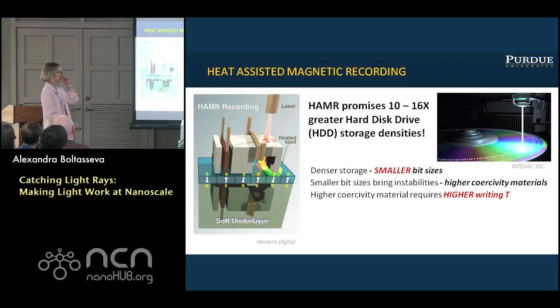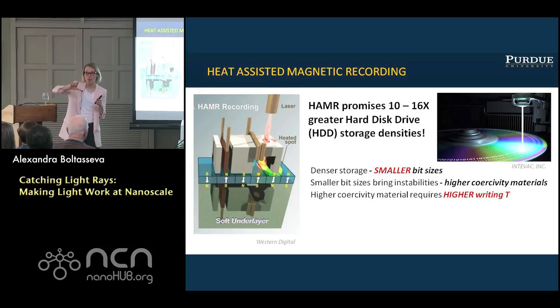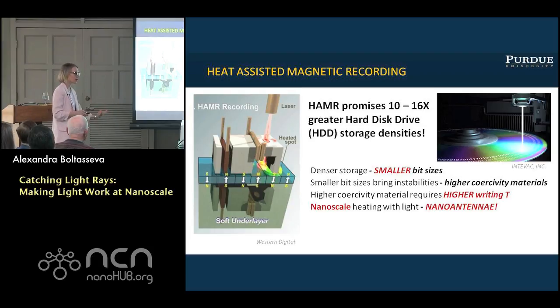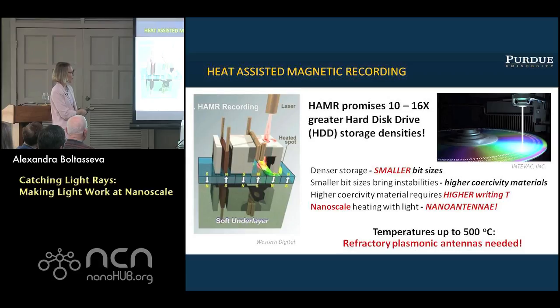In order to enable this technology, if you want to reduce the size of your bit, it's tough, because the smaller the size, the more instabilities. Your magnetic moment is always flipping. So if you want to make it stable, you have to use high coercivity materials, and the writing temperature should be high. Now, how do you heat things up on a scale of 10 nanometers? Only an optical nanoantenna can do that. You are reaching temperatures up to 500 degrees C here by using a so-called near-field transducer. This is the same optical antenna that I talked about.